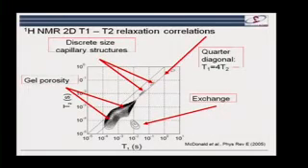This is in the liquid state, and what we're looking at here is the mobility of water. The protons are present on the water molecules, and the relaxation times, these axes here, depend on how quickly a water molecule hits the edge of a pore. I'm not going to go into the details.